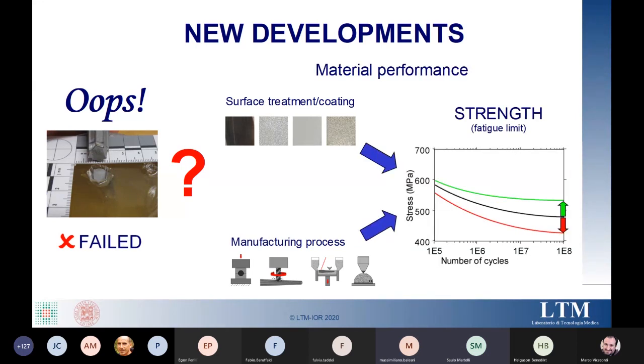In general, the problem lies in the mechanical performance of the metal alloy, specifically in the established fatigue limit. Indeed, the fatigue limit of a metal alloy is sensitive to the microstructure of the alloy and the presence of surface features, which might raise the stress induced. This means, therefore, that any new surface treatment, any new surface coating, as well as any change in the manufacturing process may have an effect on the fatigue limit of the alloy itself.